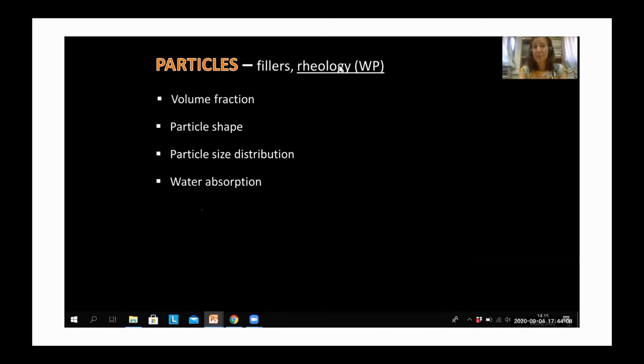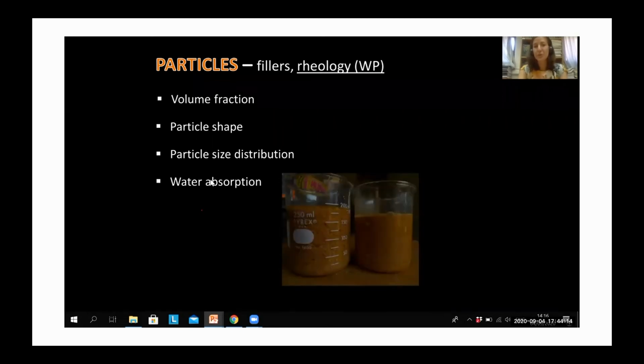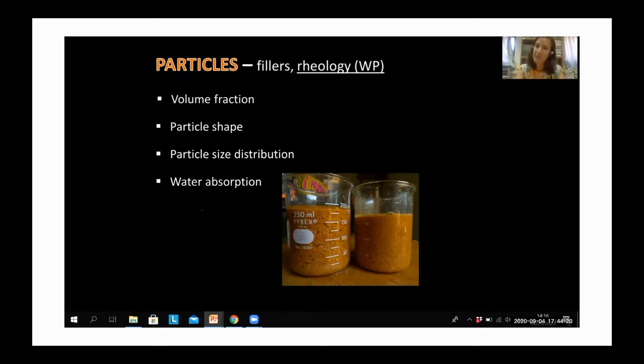Another factor in terms of controlling the rheology in terms of particle is the water absorption of them. So you know by experience for sure that there are some aggregates which are more porous than others. So for example, if we have particles of bricks, we know that they absorb water more compared to, for instance, marble dust. And so as they are porous and they are part of the suspension, if they are very porous, they may absorb already the water which is part of the suspension medium, and therefore they may have an influence on how the grout is behaving, rheologically speaking.